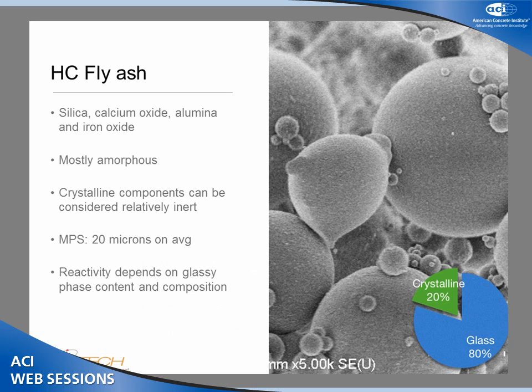So I think we all know what fly ash is, but I'll say it anyways. Main components are silica, calcium oxide, alumina, iron oxide. Class C fly ash also has pretty high contents of magnesium oxide. Mostly amorphous, higher amorphous content than Class F fly ash. Crystalline components, most people would agree that they can be considered relatively inert. Mean particle size on average is around 20 microns. And most people also would agree that the reactivity depends on the glassy phase content and the glassy phase composition.